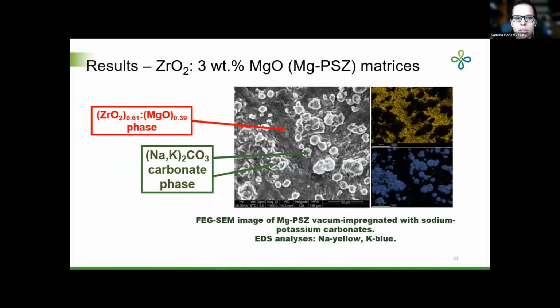And our last result is an image of a study that is being developed by a PhD student of our group, which attempts to study the conductivity of the carbonate and the entire membrane using different ceramic matrices. In this case, it is zirconia doped with magnesium oxide, infiltrated with sodium potassium carbonate. Impedance measurements are being performed to analyze the conductivity, and the permeation tests will be performed later in the chamber that we have available in the lab.